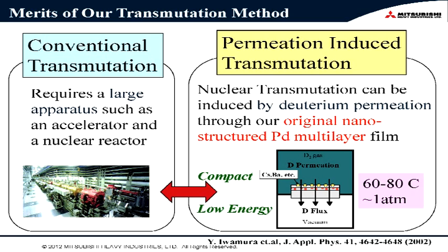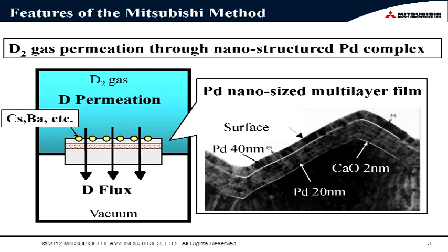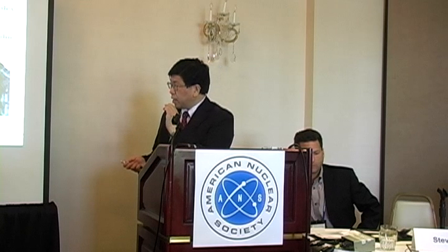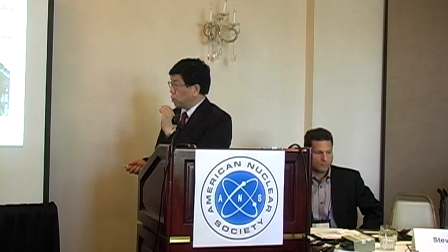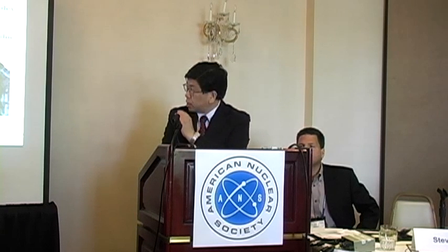This method requires not so high a temperature and not so high a pressure. We put the elements which we would like to transmute on the surface, for example, cesium and barium and other elements. We expose this side to D2 gas, and on the other side, we keep a vacuum condition. Because D2 gas and also hydrogen gas can permeate through palladium, D2 gas permeation occurs through this nanostructured multilayer thin film. After that, this element can be transmuted to another element. This is a feature of our method.